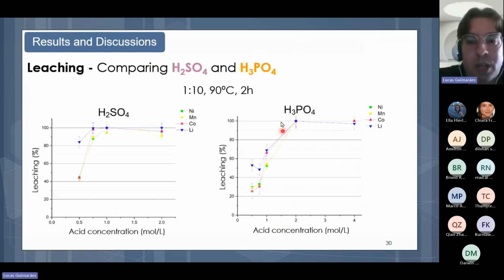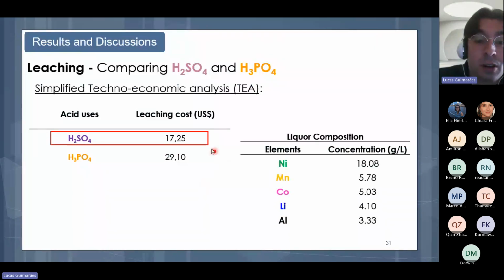So after doing as well the leaching with phosphoric acid, the two were compared, and as we can see, the best conditions of them, in order to get the same leaching efficiency of sulfuric acid, the phosphoric acid needed a higher concentration. And also a simplified techno-economic analysis, a TEA, was performed in order to know the leaching cost using sulfuric acid and phosphoric acid, and the leaching cost using sulfuric acid was the lowest. So the best results of leaching with sulfuric acid were the ones considered for the next steps.